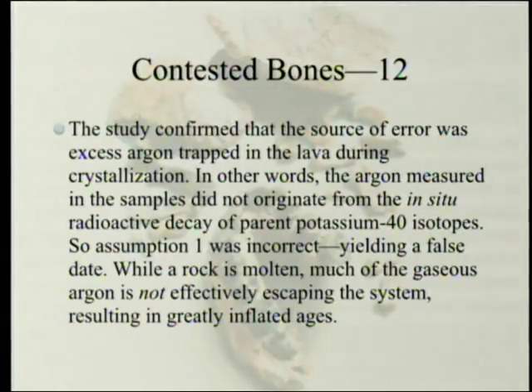The study, by the way, that study was done by creationists. The study confirmed that the source of error was excess argon trapped in the lava during crystallization. From where doesn't really matter too much. In other words, the argon measured in the sample did not originate from the in situ radioactive decay of potassium, parent potassium-40 isotopes, at least not since the volcano erupted. So assumption one was incorrect, yielding a false date. While a rock is molten, much of the gaseous argon is not effectively escaping the system, resulting in this case in greatly inflated ages.